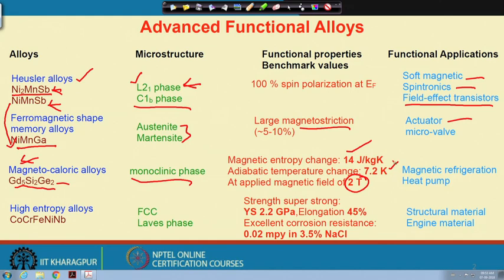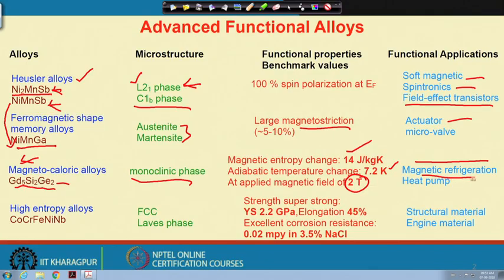This is a very fascinating class of material actually, and the benefit is simply enormous, because we can develop a Carnot cycle where on one side we will generate a hot side, and the other side is a cold side. So, we can extract that heat or we can cool a material. Because of that, we use this material for magnetic refrigeration or in heat pumps. So, both ways the Carnot cycle can be used, and the major benefit of such material we will discuss later on.